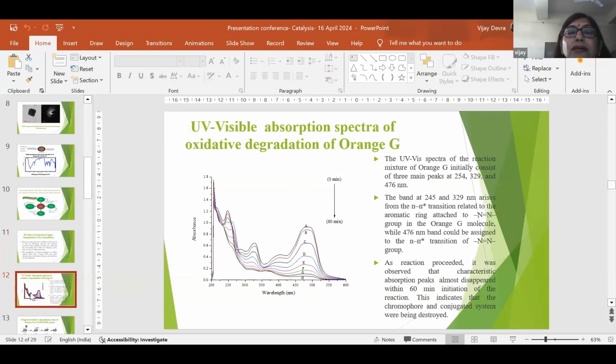Here you can see the UV-visible absorption spectra of the oxidative degradation of Orange G, an organic pollutant. As the UV spectra suggest, the reaction mixture of Orange G initially shows three main peaks at 254, 329, and 476 nanometers. The bands at 254 and 329 arise due to the pi-pi transition, which are attached to the aromatic ring of the N=N group in the Orange G molecule, whereas the 476 nanometer band could be assigned to the n-pi transition of the N=N group.